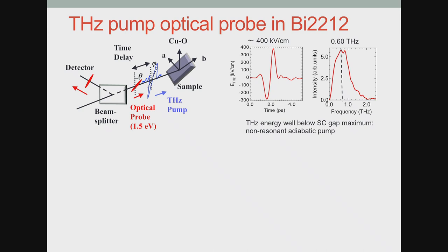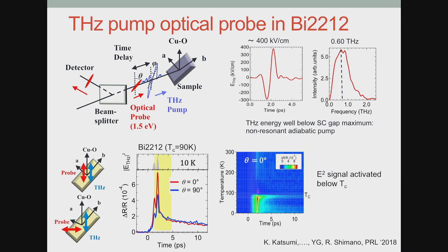So this is the form of the terahertz electric field. It's relatively high, about one order of magnitude higher in electric field than the experiment on niobium nitride, because TC is much higher. So you really need a much stronger pulse to really affect your superconducting state. And this is centered at 0.6 terahertz, so about 2.5 meV. So clearly we are in the non-resonant regime. If you look at the theoretical calculation where you see the resonance signal of the third harmonic generation peaking at delta, here we are really on the tail of it. So we are in the non-resonant regime.